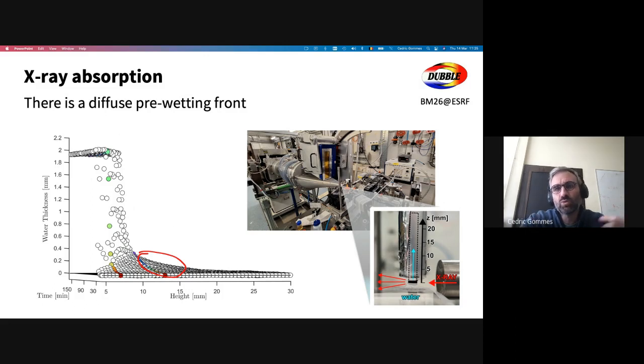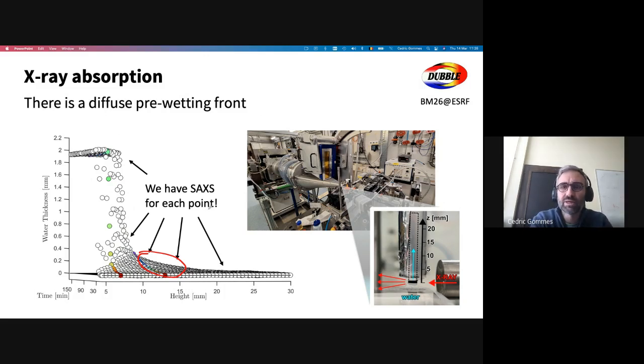So it's kind of pre-wetting, and it's quite significant. You see, it's over like 1 centimeter, right? Over 1 centimeter ahead of the main wetting front, you still have water in some form. Right? And here is where small angle scattering comes in, because for every position and every time, we have a full small angle scattering pattern. Yeah. So based on that, we can know where the water is.